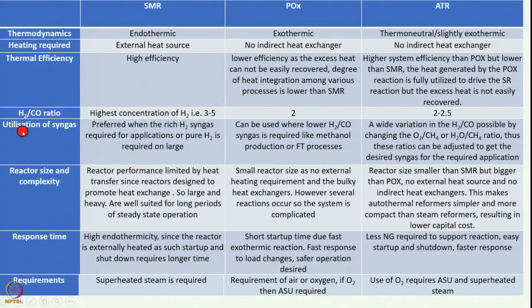If we compare in terms of hydrogen to CO ratio, it is highest in the case of SMR, where it can go 3 to 5, in partial oxidation it is 2, in fact less than 2, and for ATR this can vary depending upon the steam to carbon ratio, or oxygen to carbon ratio. So, this can be 2 to 2.5 or it can be more, we can get a wide range. Compared to partial oxidation, this is higher, but compared to steam methane reforming, this is lower.